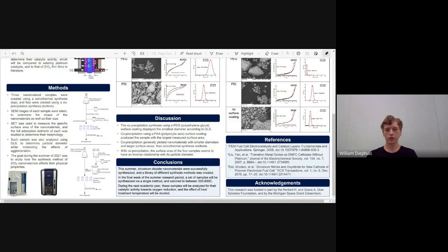For each sample, we took SEM images, which showed us the shape of the nanoparticles and told us roughly whether or not the reaction proceeded the way we wanted it to. We also used BET and DLS to measure the surface area and diameter of these nanoparticles, respectively, because surface area and diameter are very important properties for any catalyst material.